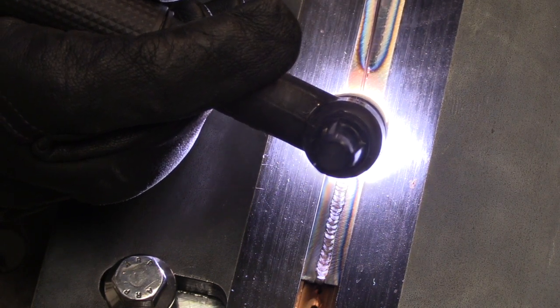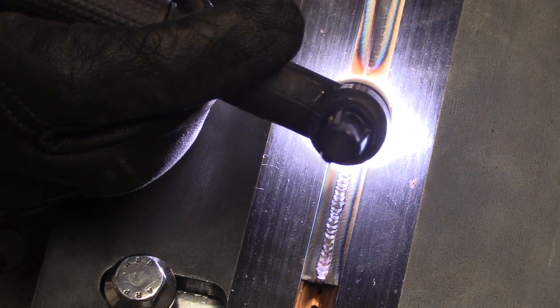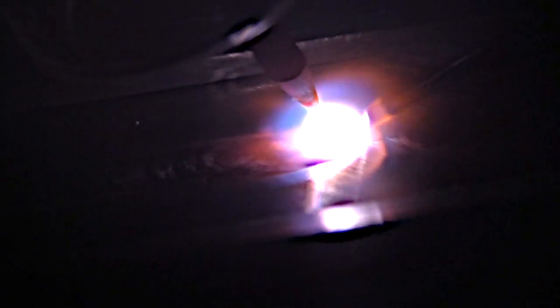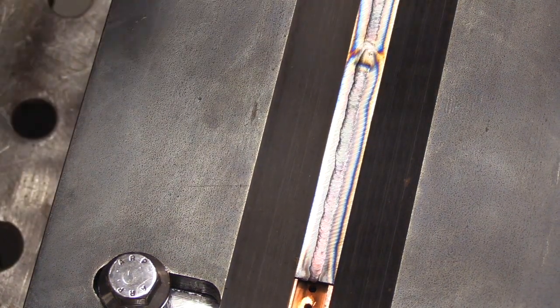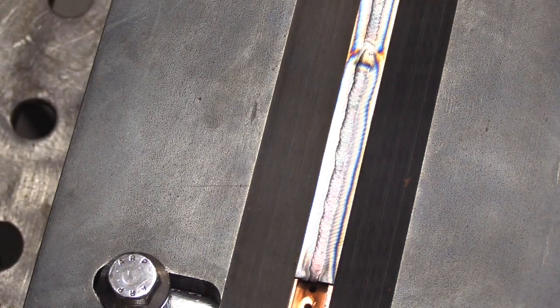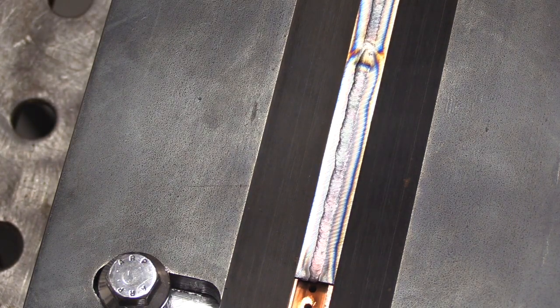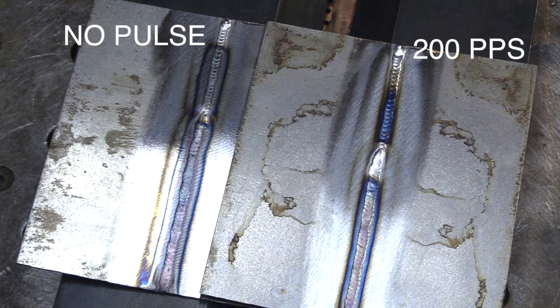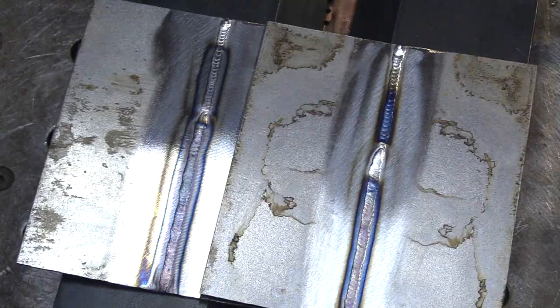All right, let's do that other half now, just like we did before. We're going to come up on that previous weld. Just the same old fundamentals. We're trying to keep a tight arc, move along at a consistent rate, keep the hot tip of the filler shielded by the argon. And as we move into that previous weld, quit adding filler, keep moving forward, taper off the amperage to 0, and that's what prevents a crater crack, especially on crack-sensitive alloys like chromoly, precipitation hardening stainless, Inconel 718, etc. There's the no pulse, there's the 200 pulses a second. Definitely a little bit of difference, not like night and day.